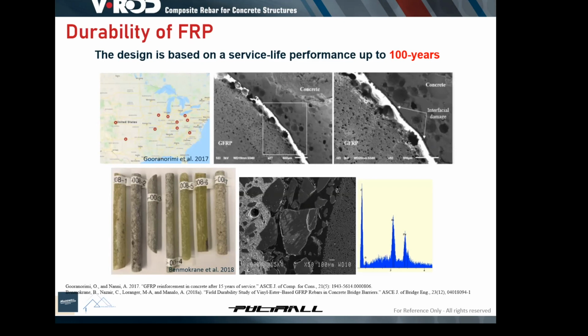Both studies put the samples under the microscopes, tested the samples for strength retention, and they didn't see any degradation of the material after this time, after 15 years, after 18 years. The University of Miami reported a degradation of less than 3%, while the laboratory tests suggest that there should be some degradation of the material after 15 years or 17 years of exposure.